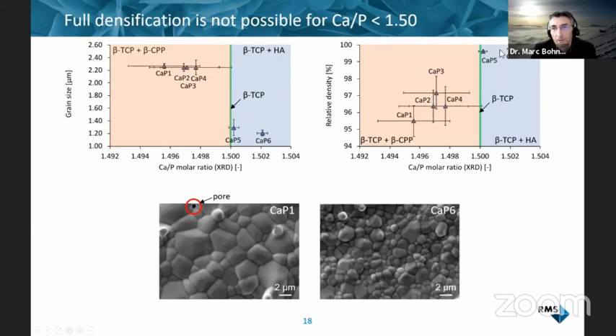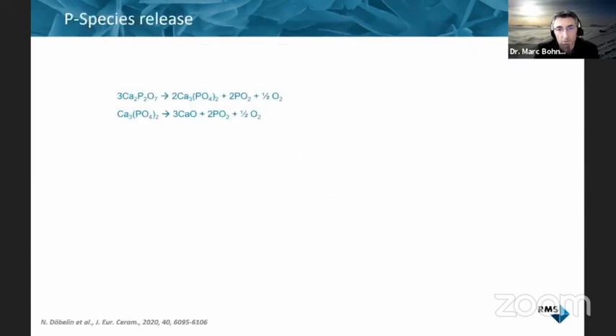If you look at the densification, it's almost perfect with a value over 1.5, and then it decreases the more pyrophosphate you have. So it's not that easy to produce samples that have the same grain size, the same density, and that could be considered as identical more or less for the cell culture studies.